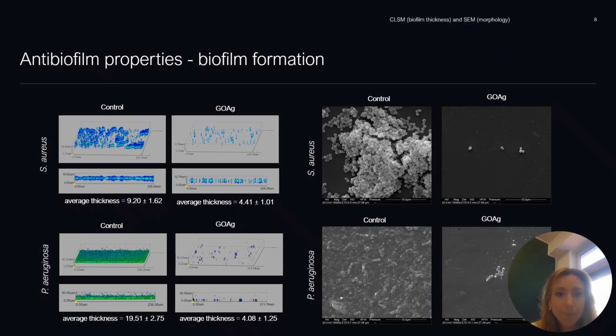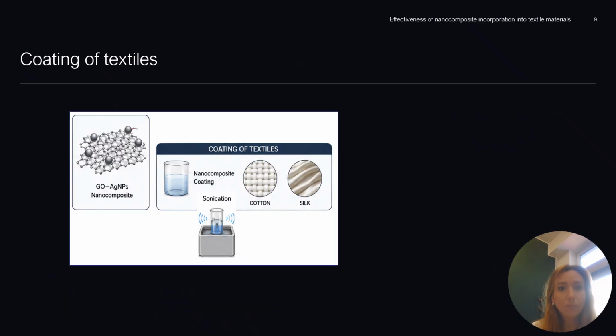on the surface. Together, confocal and scanning electron microscopy analysis clearly demonstrate that the silver nanoparticles with graphene oxide, the nanocomposite, effectively inhibits biofilm development, disrupts mature biofilm structure, and significantly reduces bacterial colonization. Encouraged by the strong antibacterial and antibiofilm activity of the nanocomposite, we proceeded with textile functionalization.